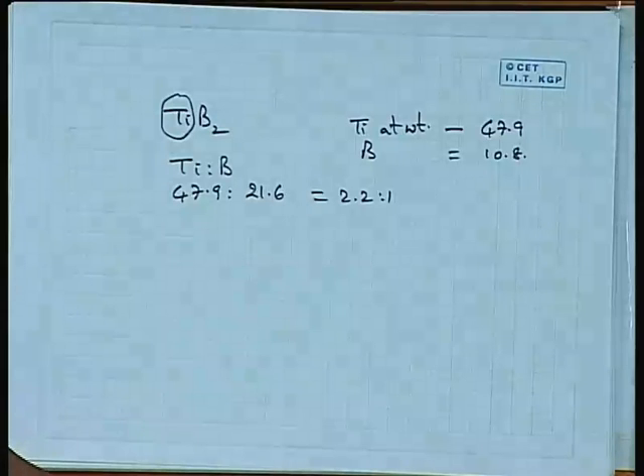That means when you take the titanium and boron, when you are making the aluminum titanium master alloy and aluminum boron master alloy separately, you have to make sure that the titanium content of the aluminum titanium master alloy is 2.2 times the boron content of the aluminum boron master alloy. That has to be controlled.